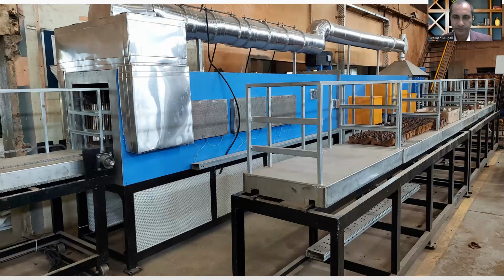That's right. During your presentation, you talked about absorbing, transferring and reflectors. So you said that the cores, particularly silica sand cores, are the absorbers. Correct. It is because of the permeability that we have in the core. Because of the permeability of the sand core and the water moisture available, they become absorbers. And glass is the total transfer. Not all glasses. If it is borosilicate glass, it also absorbs. But if it is pure silica quartz glass, then it is transparent.